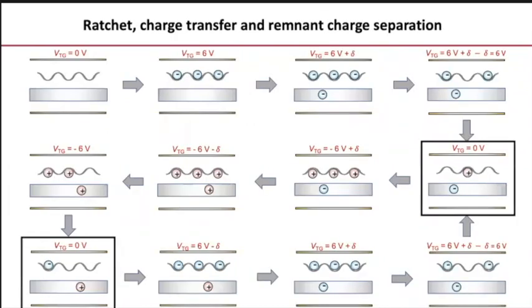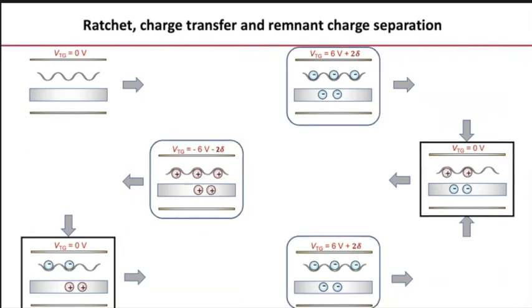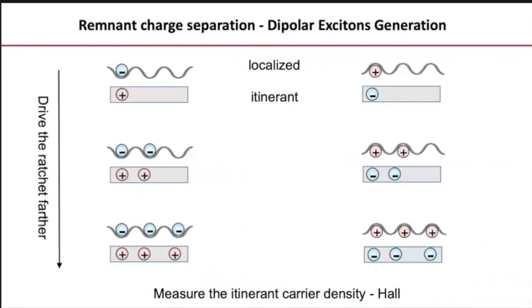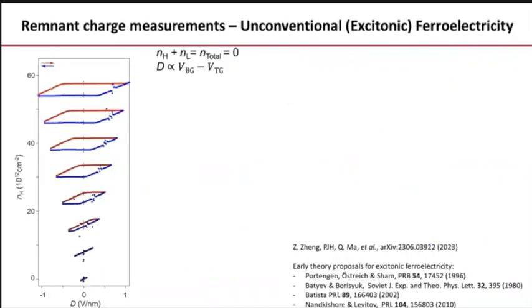The way this process takes place is explained here. I think I'm running out of time, so I'm going to skip it, but the paper is posted in the archive. You can look at it. You can do this in larger steps or up to further displacement field, and you can generate pairs of electrons and holes. So this remnant charge separation, which is measured through Hall measurements, gives you a type of unconventional ferroelectricity when you have these hysteresis loops, which are continuously growing by applying this displacement field further and further.